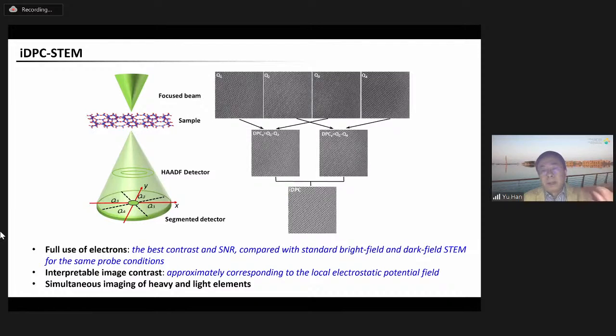However, because STEM uses a focused beam, the instantaneous electron dose is much higher than in normal TEM mode. Therefore, STEM usually leads to more severe irradiation damage effects than normal TEM. So for electron beam sensitive materials, STEM imaging is considered more challenging than normal TEM imaging. But recently, a new STEM technique called iDPC-STEM emerged as a promising method for imaging sensitive materials.